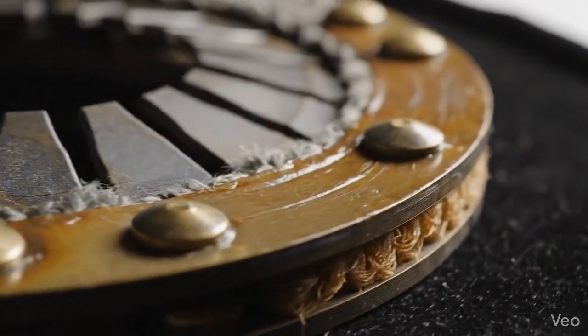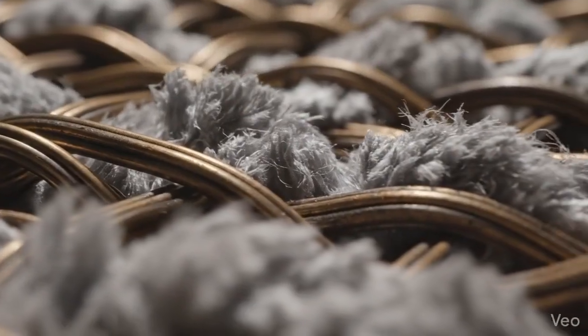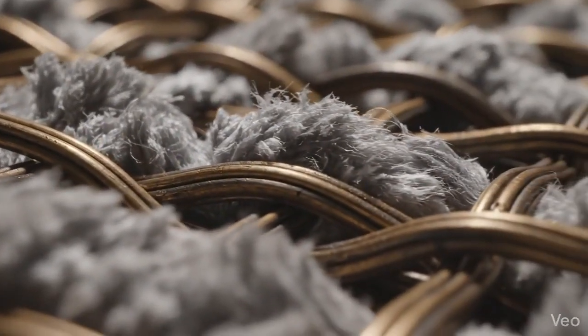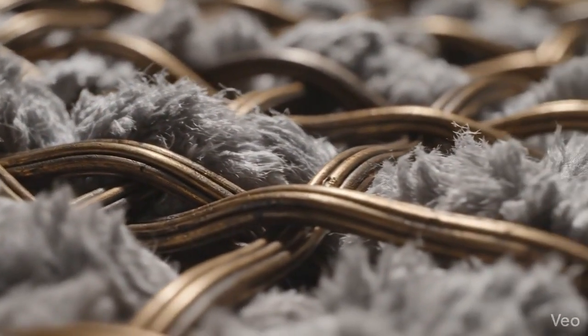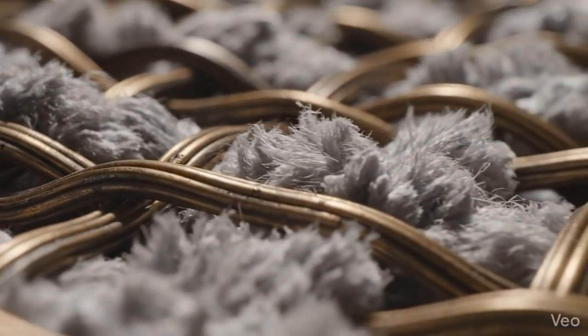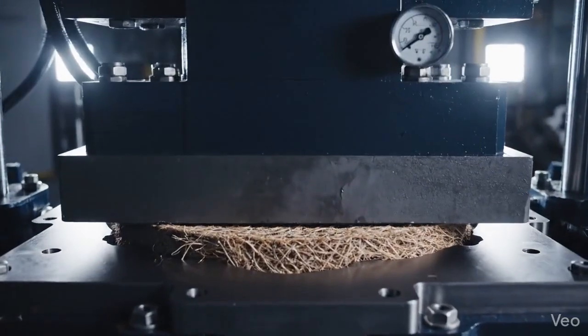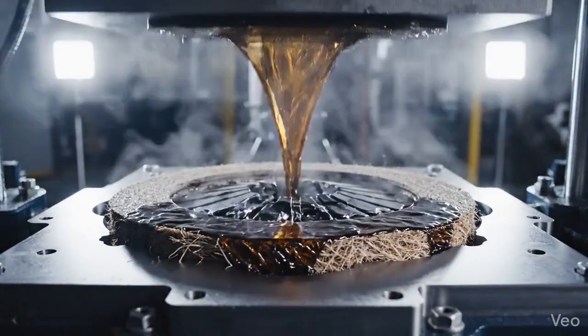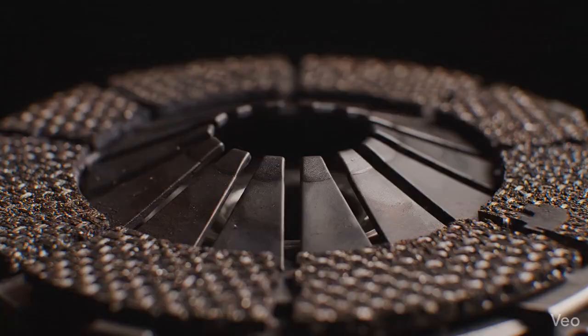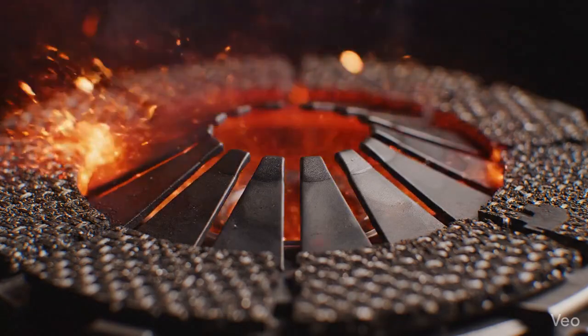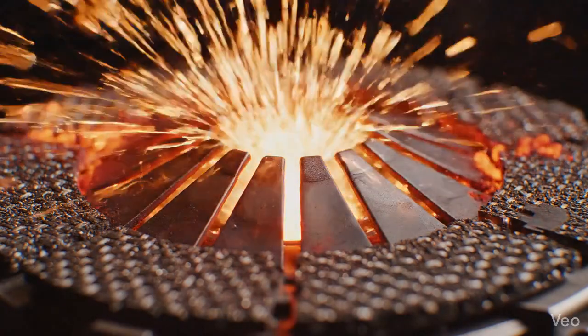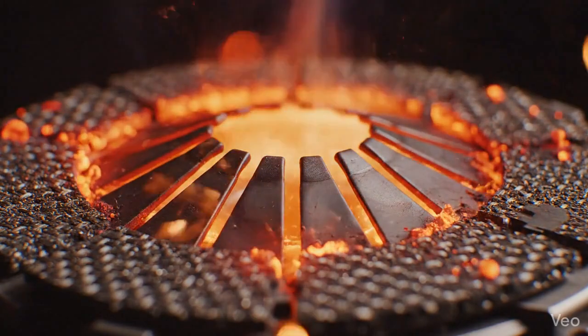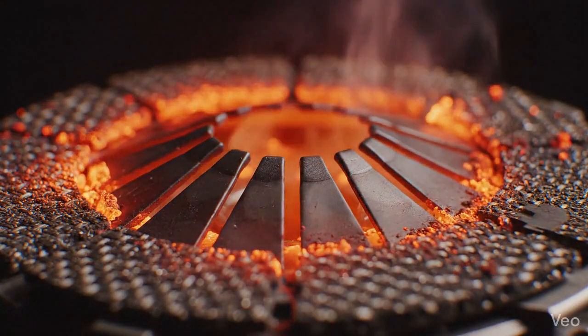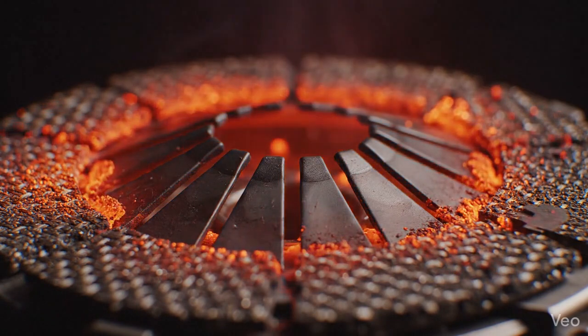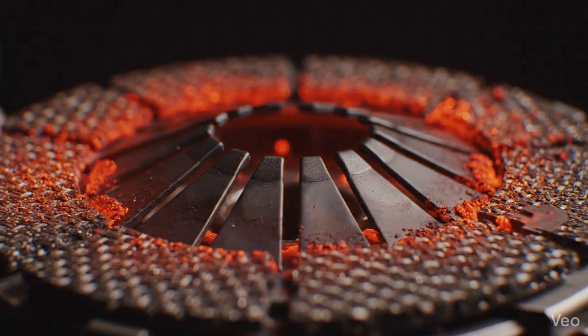The asbestos fiber used in clutch disc facings was typically woven into a composite matrix, reinforced with brass or bronze wire for additional structural integrity, then impregnated with a binding resin under compression. This produced a facing that resisted heat fade under sustained engagement loads, which is critical because the alternative is a clutch disc that glazes and loses bite progressively as it approaches its thermal limit.